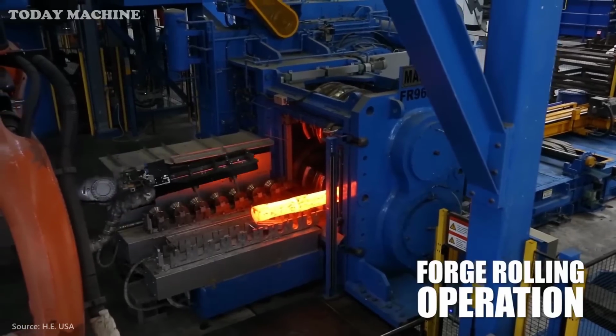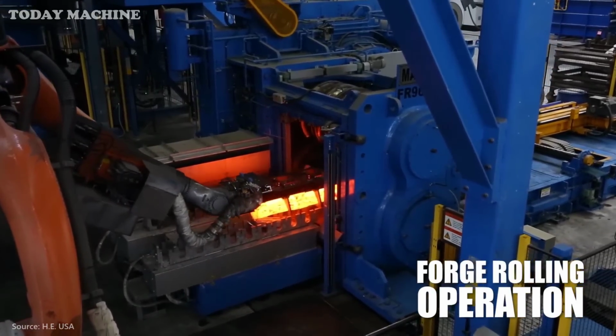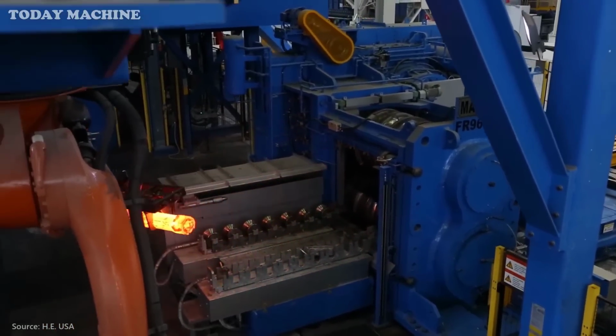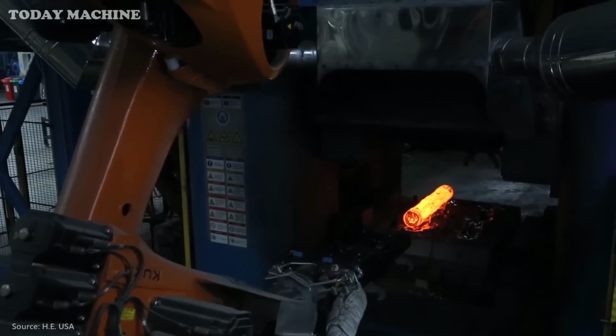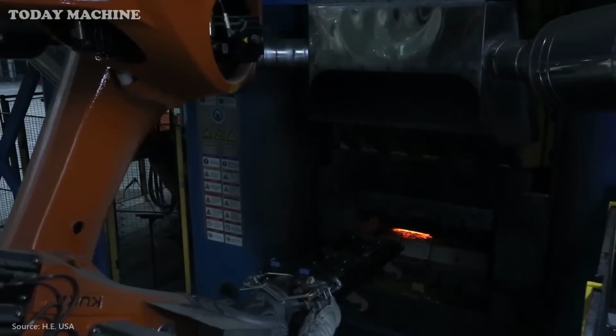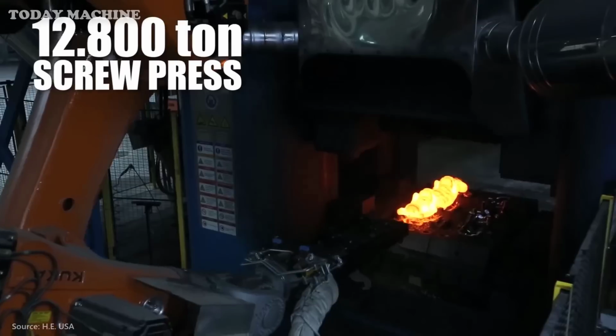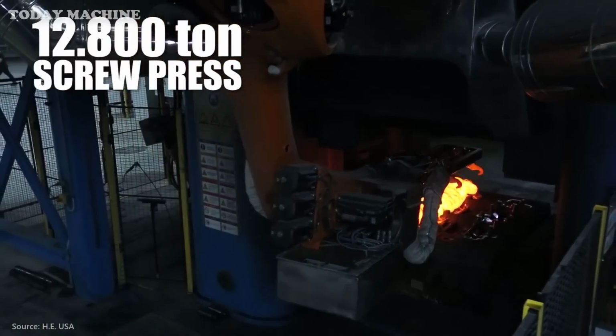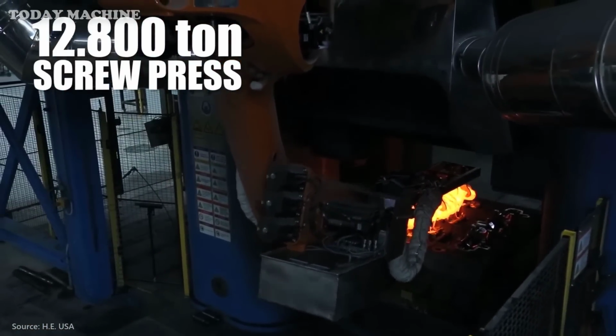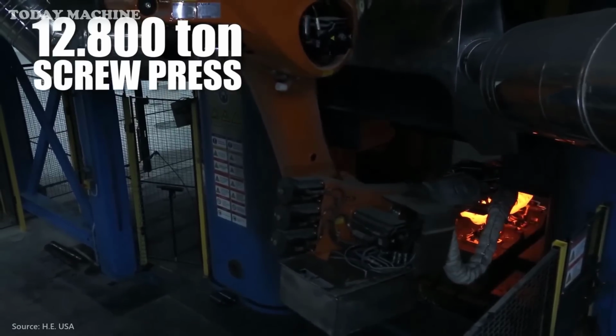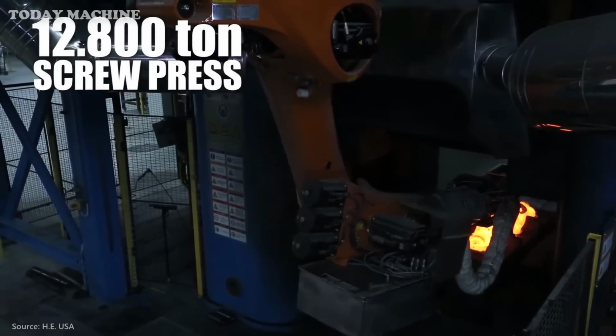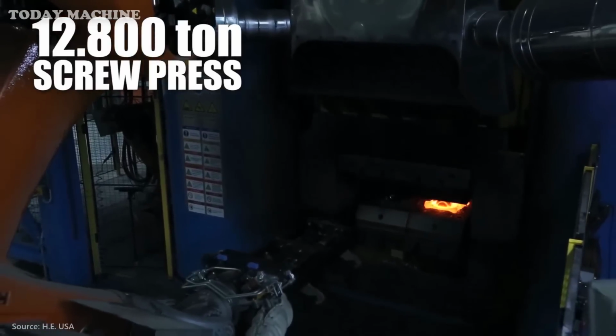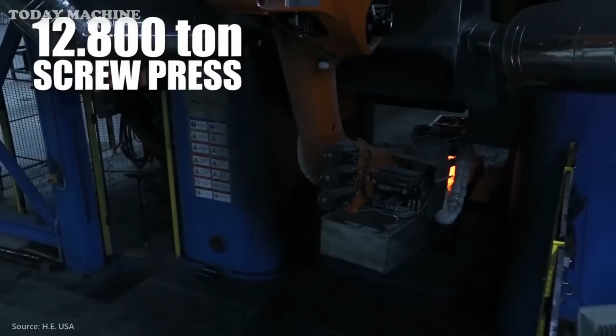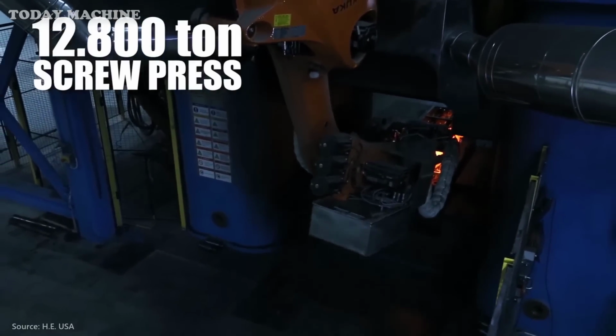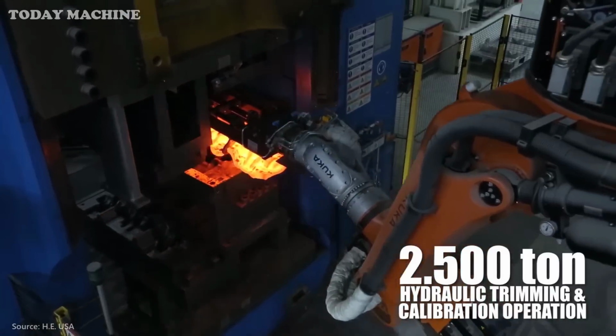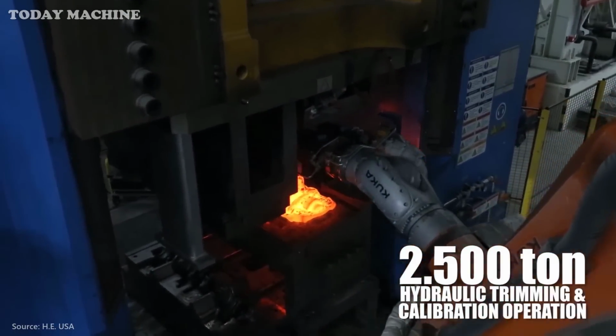In a forge rolling operation, the forged billet is progressively shaped through a series of rolling steps. This step ensures the crankshaft achieves the precise dimensions and surface quality required for its critical role. A 12,800-ton screw press is often used to exert the necessary force for the forging, followed by a 2,500-ton hydraulic trimming and calibration operation. This stage trims excess material and ensures the crankshaft is within the desired tolerances, improving its overall fit and performance.